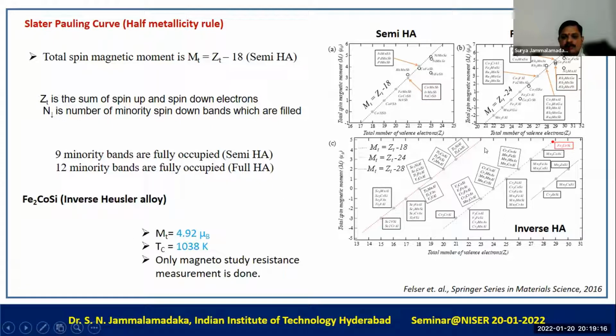So among all these compounds, Fe2CoSi is a quite promising compound because it has a very high magnetic moment, 4.92 Bohr magneton, and a Curie temperature of the order of 1038 Kelvin. But although it shows attractive magnetic properties, very few experiments have been conducted on this compound. So that is the reason why we were very much interested in exploring the domain wall dynamics and other properties on this compound.